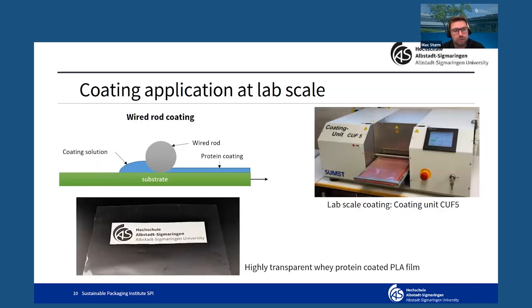So in the Preserve project, we first started with the application of the whey protein based coatings at a lab scale. So it was applied to an A4-sized sheet with this coating unit you can see here. The process works like this. The coating solution is spread here in front of this wired rod. It's also illustrated here, and then spread on the substrate evenly, and the remaining water removed by heat. The resulting film you can see here on the bottom. This is a whey protein coated PLA film, and as you can see, it's still very transparent after it's been coated, which is also quite important for many packaging applications.